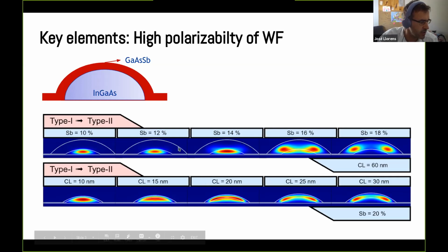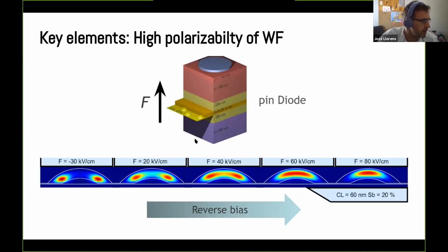So this allows some wave function engineering, but this is static. Instead, if we introduce these quantum dots inside a pin diode, and we play with the applied voltage, and also with the electric field that the quantum dot is sensing, what we can achieve is an active control, because by applying the electric field, the hole can be pushed either from the bottom towards the top. And as it is in a type 2 band alignment, the geometry changes from ring-like to quantum dot-like. So this gives us a lot of control on the orbital part.